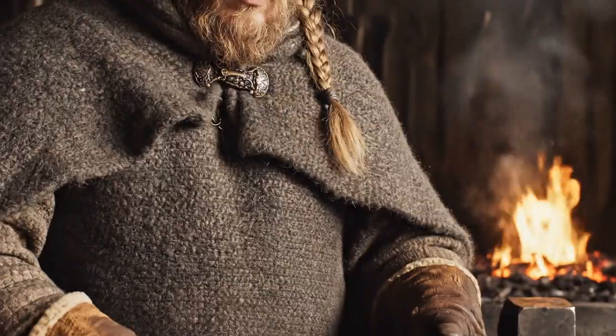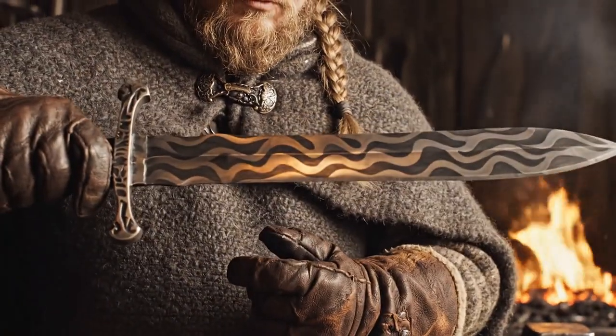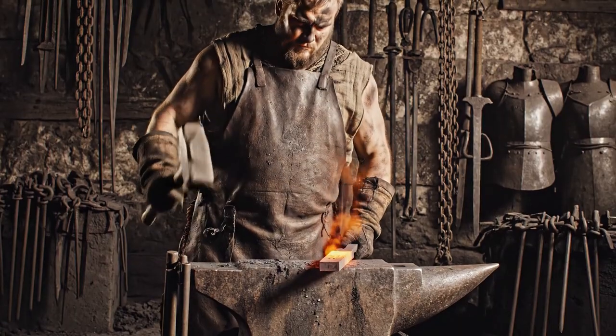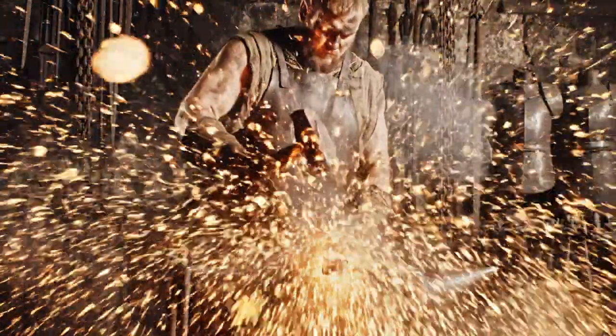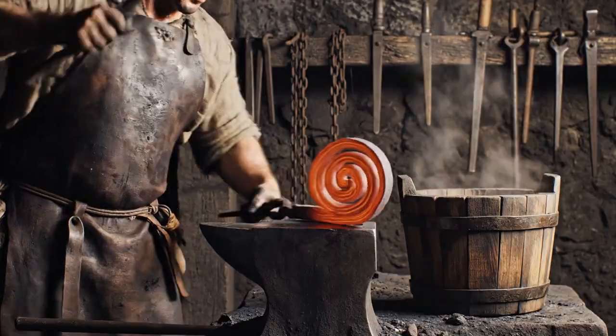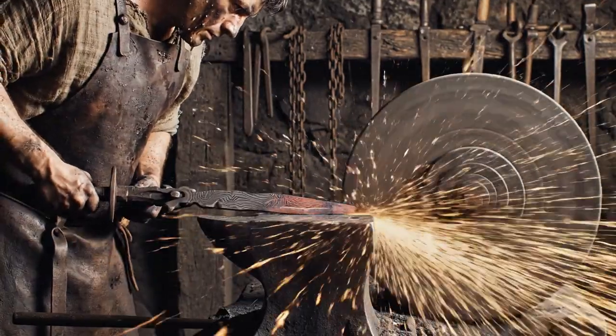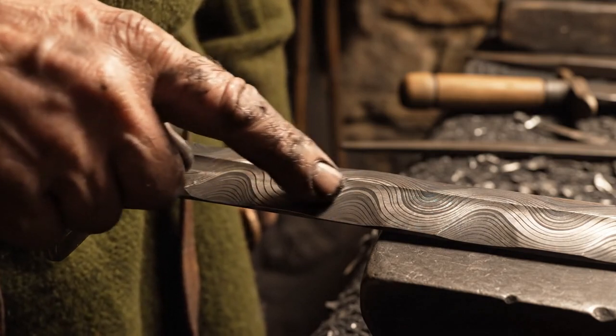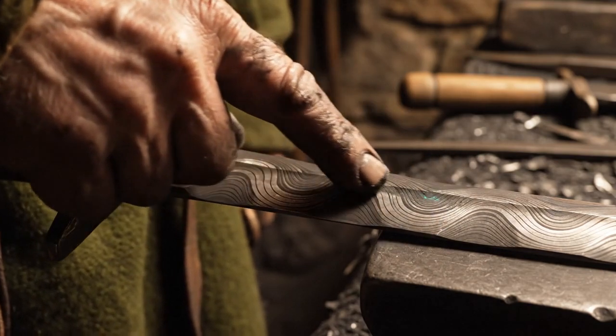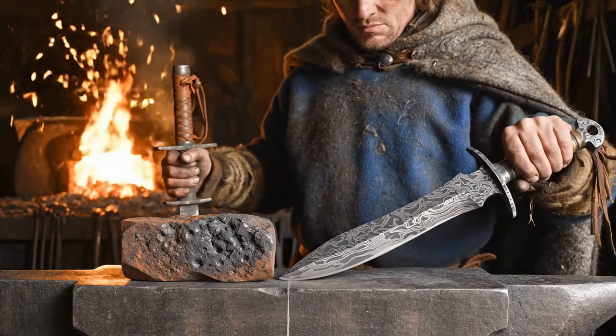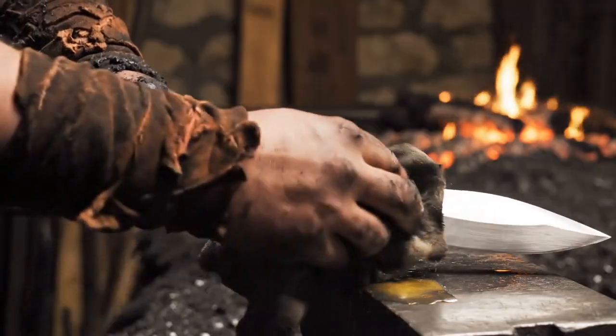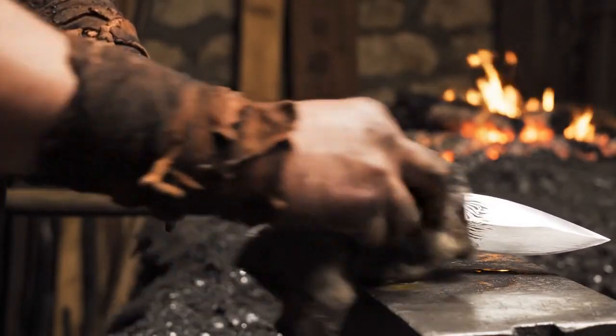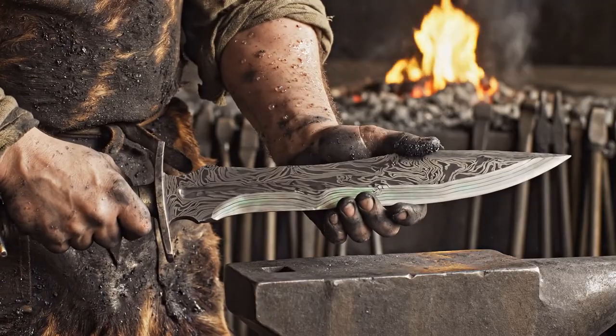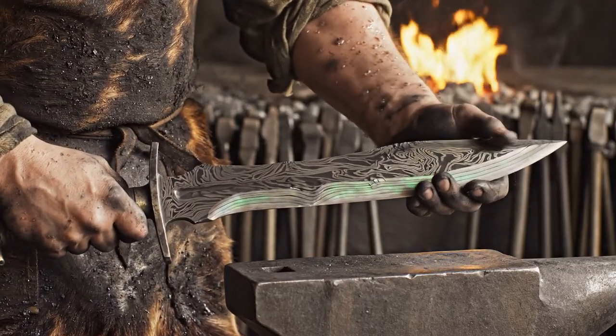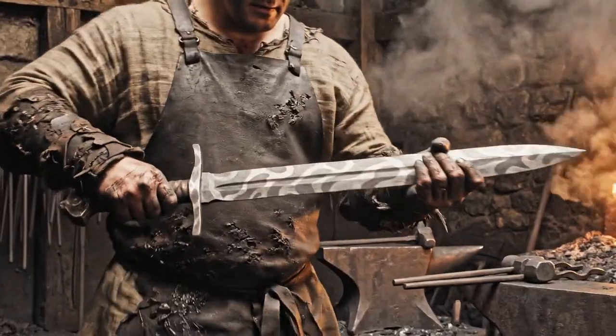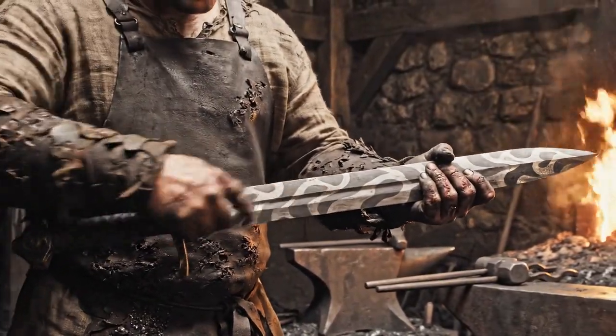The most dramatic demonstration was in pattern-welded sword blades. Between the 5th and 14th centuries, European swordsmiths created blades by forging together, welding alternating strips of different types of iron, then twisting and grinding them to produce serpentine patterns on the blade's surface. Phosphoric iron from bog ore was used as one of the contrasting metals precisely because it corroded at a different rate than the layers of common iron and steel. When the blade was etched with mild acid, the phosphoric iron remained bright, while the other metals darkened, creating a striking visual contrast. The pattern welding technique depended on the corrosion resistance of bog iron to make the decoration visible.